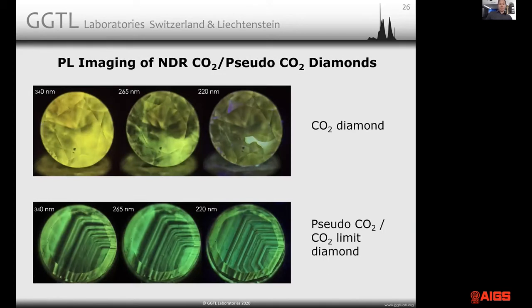PL imaging: here we have two samples, a CO2 diamond on top and the stone that's actually a limit between CO2 and pseudo CO2. They have sometimes rather dramatic luminescence images, as the bottom stone shows. At 220 nanometers, it's like a piece of art, this kind of fluorescence image.